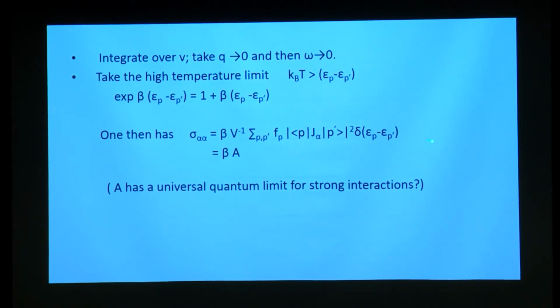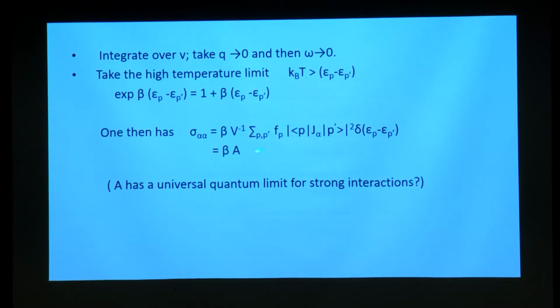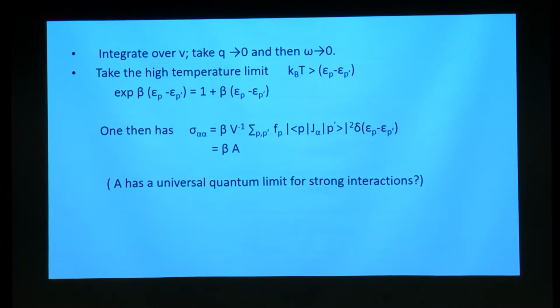Now, what does it show? It shows that conductivity can go as the inverse of temperature, and so resistivity can go as temperature. Of course, this coefficient is shown here, but I haven't been able to calculate it. It is quite possible that there is a universal quantum limit to this coefficient for strong interactions, which could be due to electron-phonon interactions, electron-electron interactions, and so on.